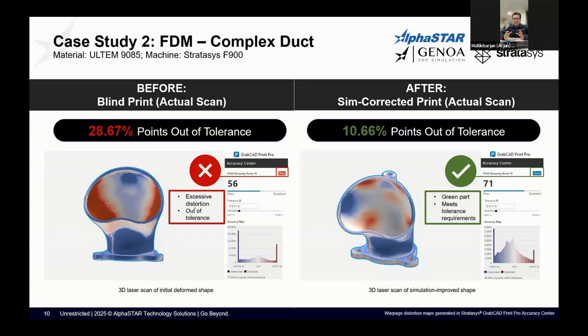So once we predict that deformed geometry, we create a compensated geometry out of our predictions, and then tell the system to, okay, now go ahead and print this compensated geometry so that you'll have a better chance of getting a green part, first time right part. So that is what we did on the right hand side. We simulated it, we predicted the deformations, we created compensated geometry, sent that compensated geometry back to the slicer and asked the machine to print.